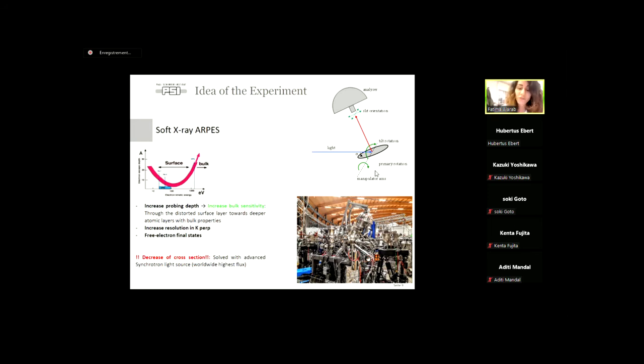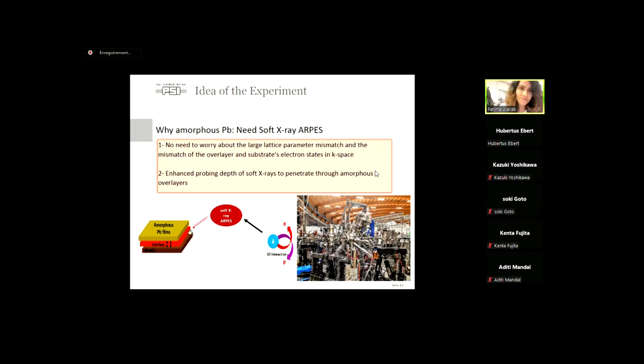However, in our case, because we are using a very advanced synchrotron radiation where the flux is very optimized as well, we have a very high photon flux that basically recovers the loss in the cross section. All right, and then we have a very high number of photoelectrons afterward. So because of this, we could use amorphous overlayers because we will not worry about the non-crystallinity of the overlayers, and we can go through them to reach the interface where we basically are going to modulate the spin-orbit interaction. So this is one thing.